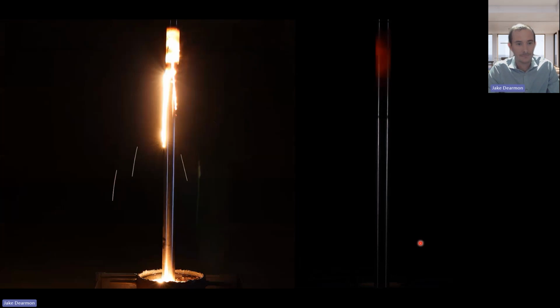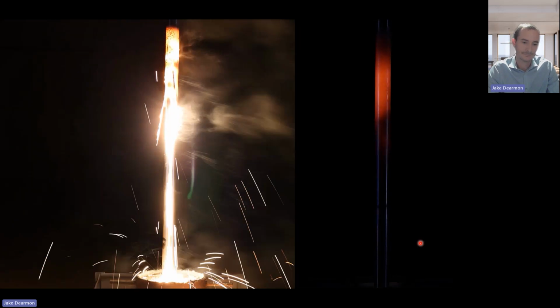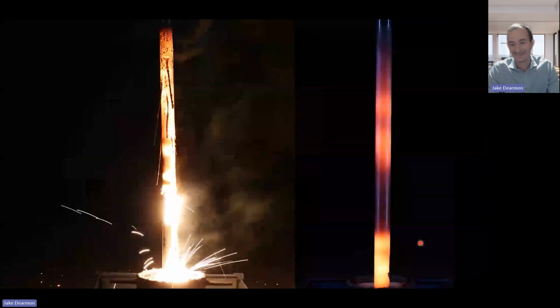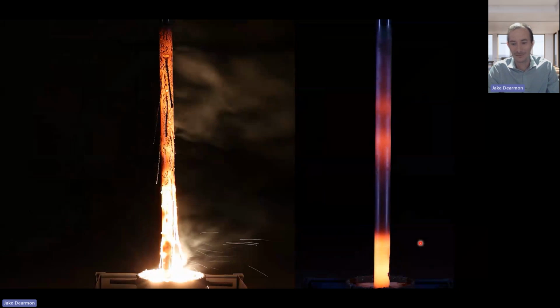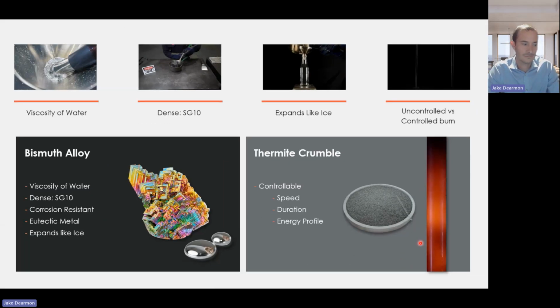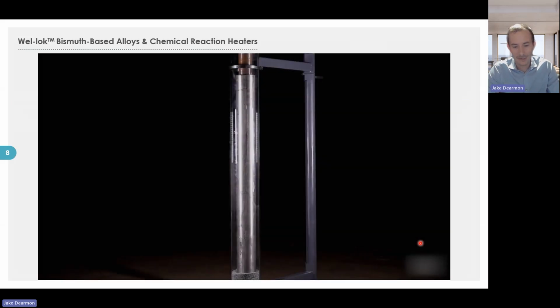So on the left-hand side here, we're seeing the thermite burn. It's burning through the heater. Obviously, we don't want that downhole. That's not good. On the right-hand side there is one of our thermite mixes we use every day in that same heater pipe. And you can see how it's controlled all the way down. We're able to focus the hot spot of that heater where we want it, and able to actually melt the alloys in a way that's beneficial for us. So that's kind of the two pillars of technology. You combine those two together and you get what we call the wel-lok technology.